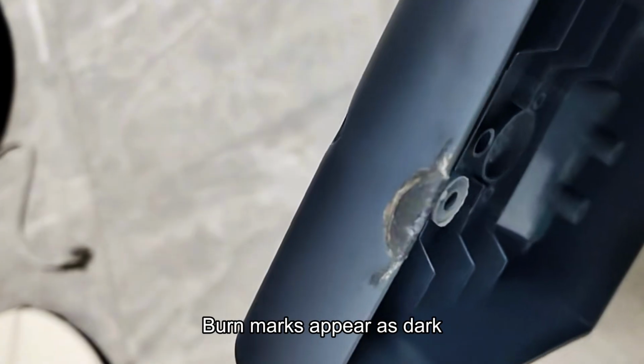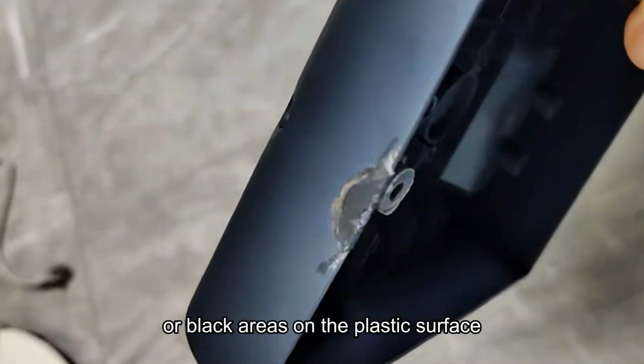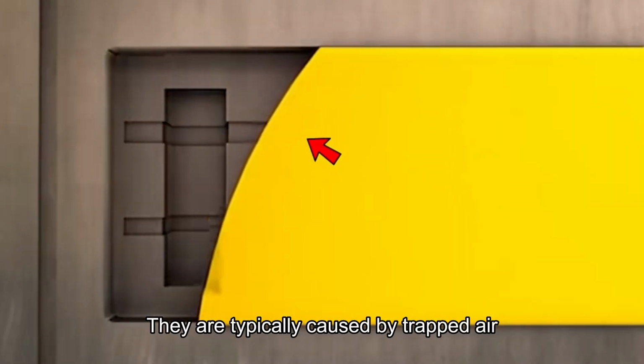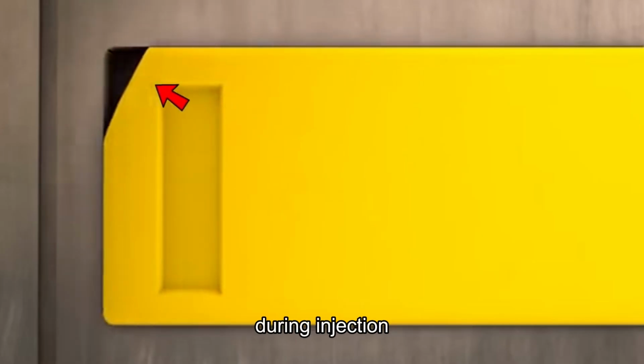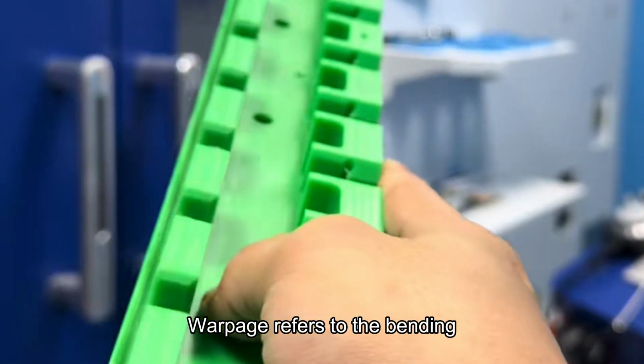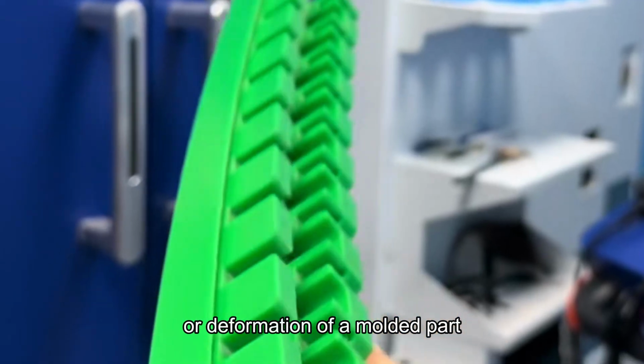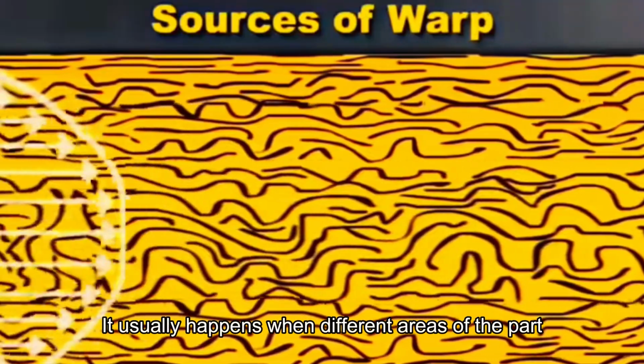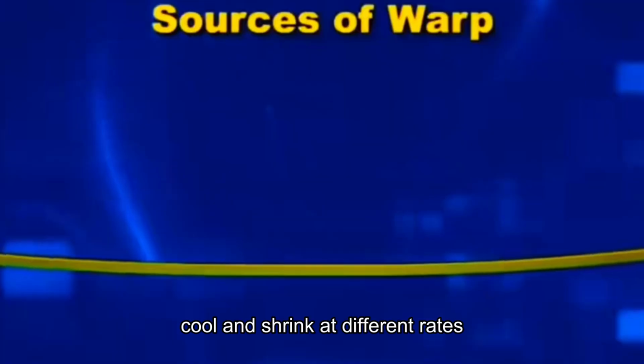Burn marks appear as dark or black areas on the plastic surface. They are typically caused by trapped air that becomes compressed and overheated during injection. Warpage refers to the bending or deformation of a molded part. It usually happens when different areas of the part cool and shrink at different rates.